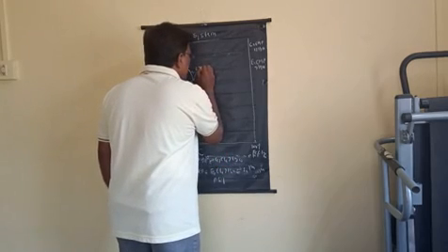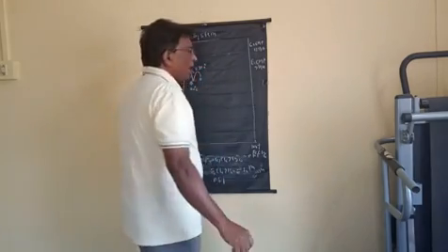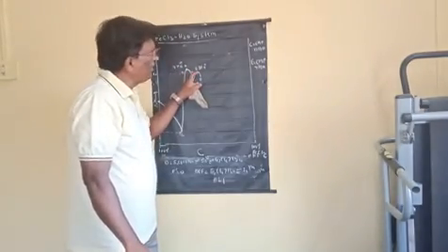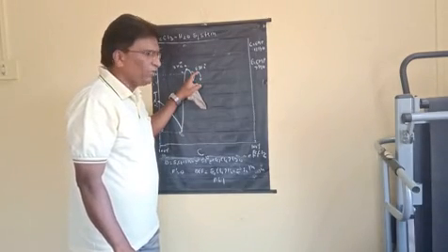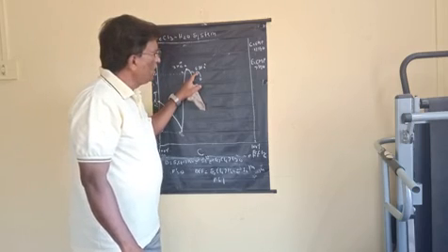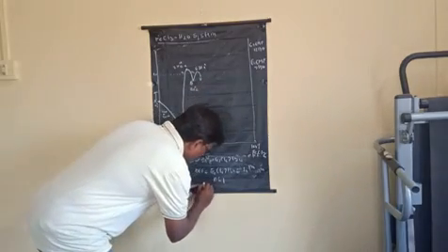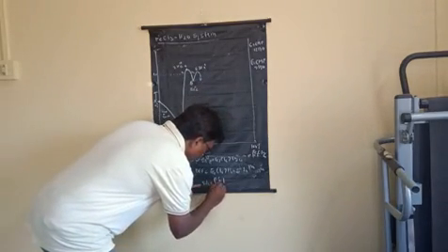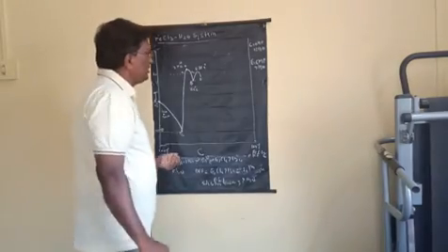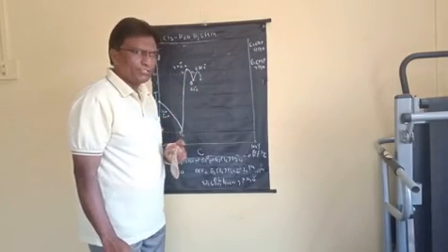The temperature is 32.5 degrees centigrade, and here again the system is non-variant because here the two component system becomes one component, and therefore the degree of freedom is 0 according to the reduced phase rule. Now this is called the solubility curve of the heptahydrate, that is Fe2Cl6·7H2O. Solubility curve of the heptahydrate.